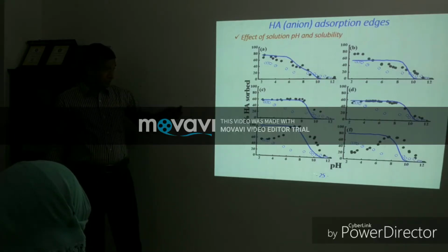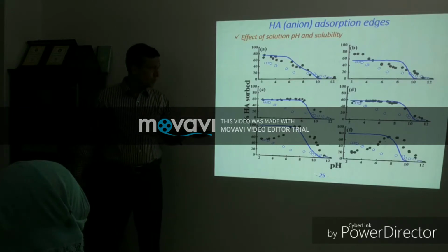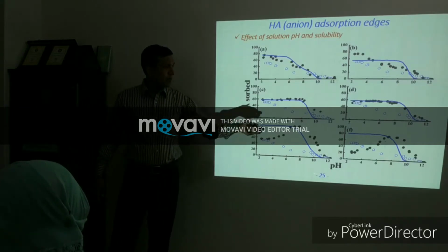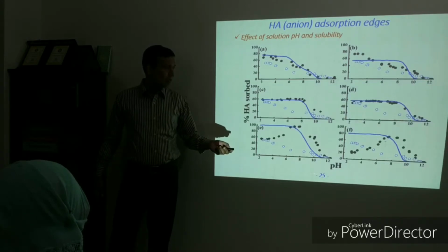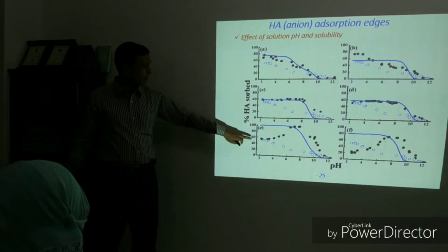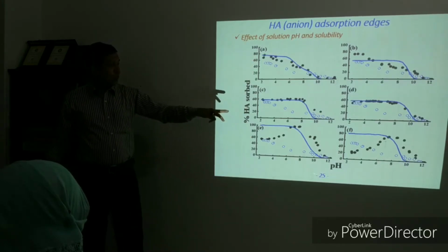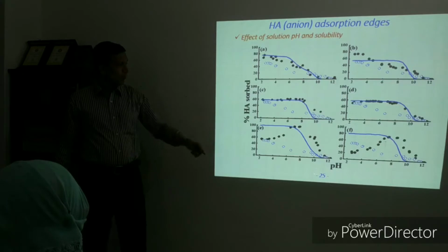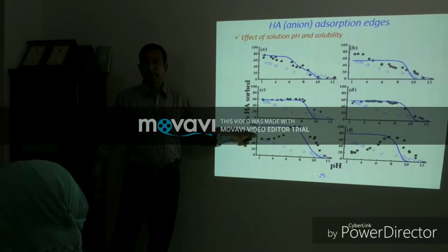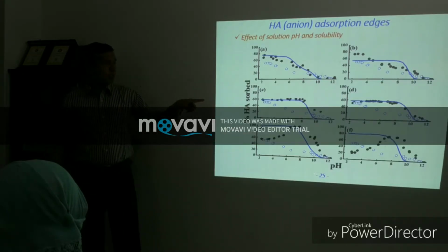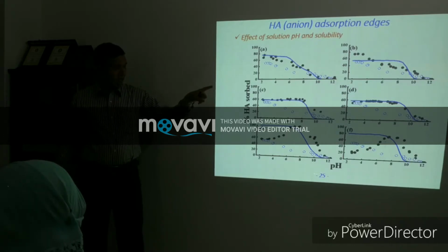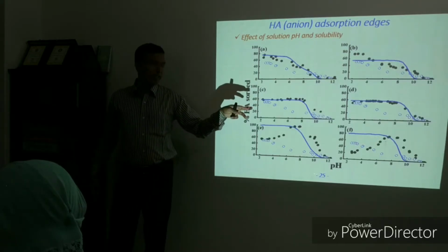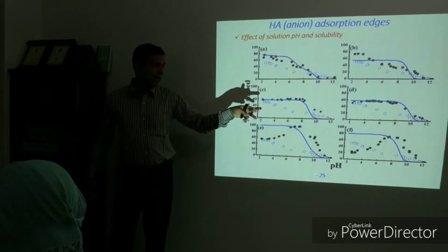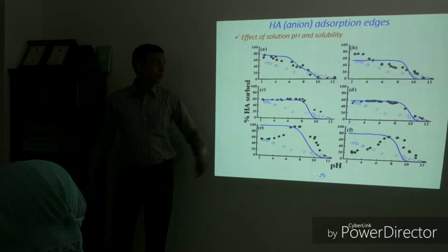And it is very interesting to see here for the manganese aluminum binary oxide, which has been prepared by mixing this and that. So we see that the adsorption behavior is looking like this. That means in the case of mixed aluminum manganese oxide, boehmite is dominating humic acid adsorption due to its higher point of zero charge.